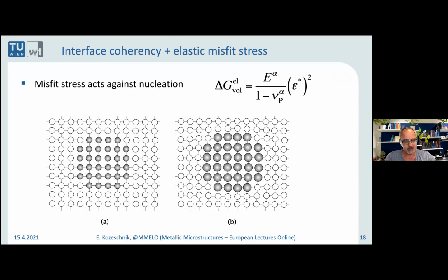The talk here is about metallic microstructures. And the metallic microstructure is usually one which is crystalline. And in contrast to raindrops that form in a cloud, we have some limitations here in the solid state case, and that is related to the crystal structure. And I've plotted a precipitate on the left side, which is coherent with the matrix.